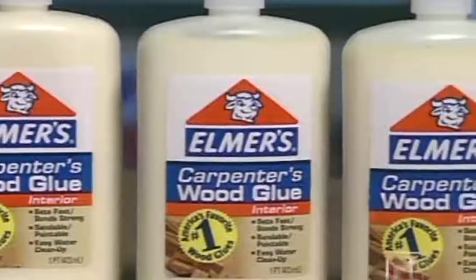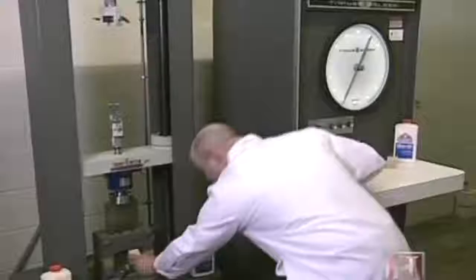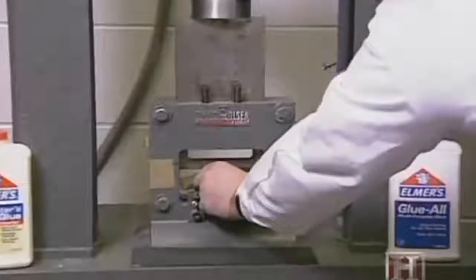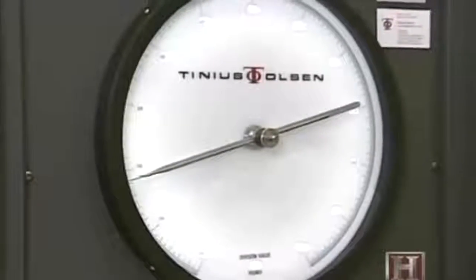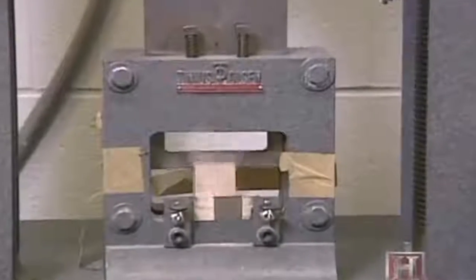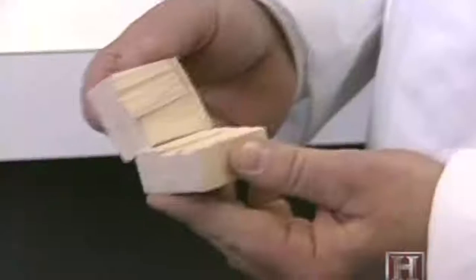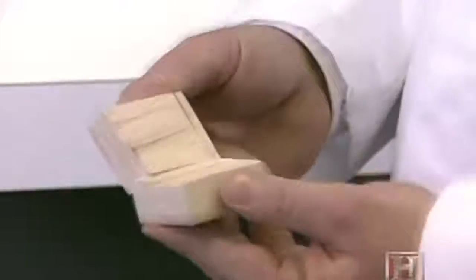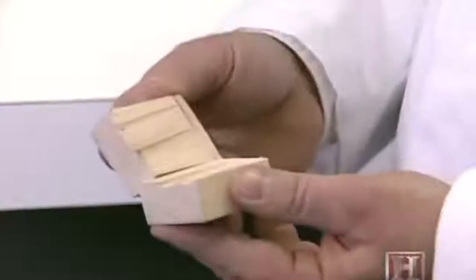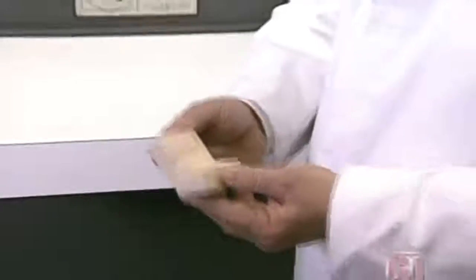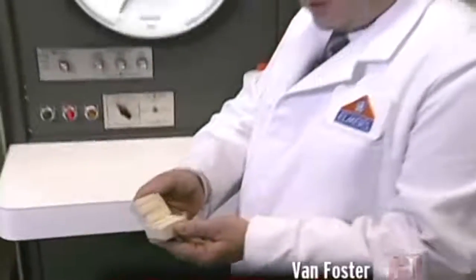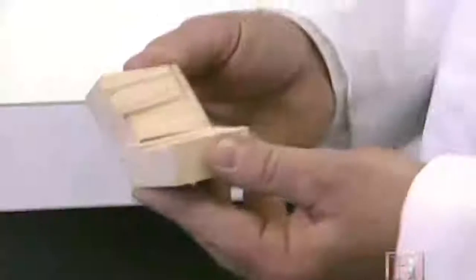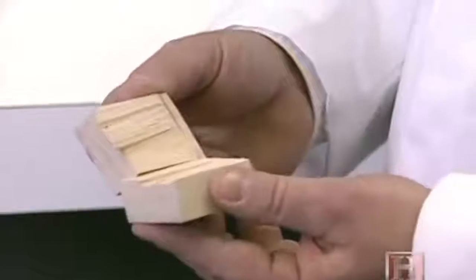A simple test of a wood glue bond, in this case Elmer's glue, demonstrates the strength of the bond versus the substrate, the wood. Good wood glue should have not only good strength, and in this case you have around 3,500 pounds per square inch, but a good wood glue should also have what we call substrate failure. In this case, the wood was actually pulled apart, which means the glue was actually stronger than the wood itself.